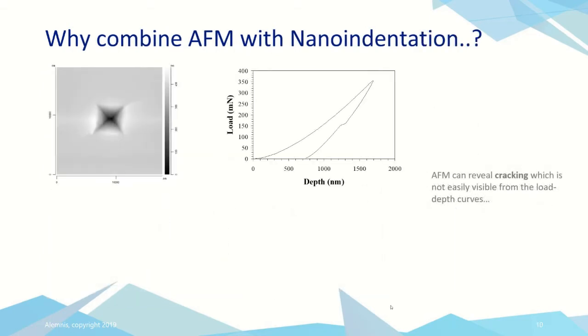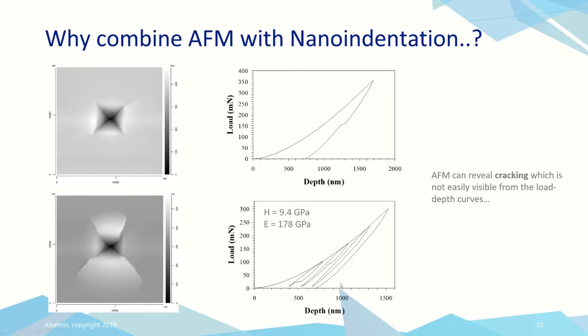Here's another example. This is an indentation on a silicon wafer, a single cycle, and you can see the cracks emanating here out from the corners of the indentation. And if we do a multi-cycle on that material, you can see from the curve the multi-cycle is clearly defined, but we don't know how much cracking is actually happening. Here we see from the image that we've got both lateral cracking and subsurface cracking going on around the indentation site.